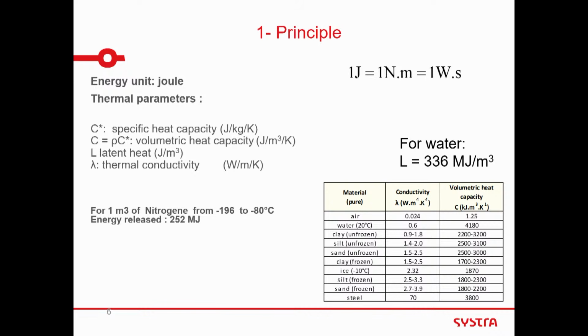So as you can see, for clay particles, silt particles, sand particles, in fact, globally the same, in unfrozen state. For ice, you see that the conductivity is 2.3, so it's not so different from the particle of soil. The volumetric heat is 1,800, a little less than for the soil particle. In the frozen state, it's still more or less the same: 2.3 and 2,200 for volumetric heat, which means that we need about 2,000 kilojoule per cubic meter of silt particle in the frozen state, compared to 3,000.